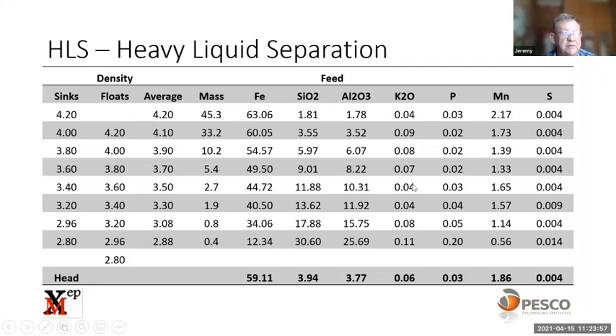So here's an example of a float-sink analysis of a Northern Cape iron ore. The density range covered was from 2.8 up to 4.2. And there was a mass distribution in each density bin and the Fe value. So you can see at the high densities, you've got high Fe. And as your density bin drops, or your density fraction that you're testing, the Fe drops. And then the silica has got the opposite response. So at high densities, you've got low silica, but at low densities, you've got high silica. This sample had a head grade of 59 Fe and 3.9 silica, but you can see the alumina was very high, 3.77. And that was one of the challenges with this specific sample.